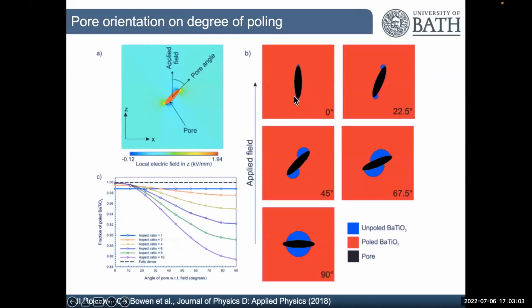And we do that by alignment of the pores. So we take our pore phase and we consider aligning the pore along the direction of the applied electric field. So in this case, I'm applying my poling field through the thickness of the material. And if I align my pore at 90 degrees to the electric field, because the field will focus in the pore, the region of ceramic above and below the pore will experience a low electric field, so it won't be polarized. So clearly there's a benefit by taking highly anisotropic pores rather than round pores and aligning them within the electric field to maximize my level of polarization and minimize the low field regions around the pores.